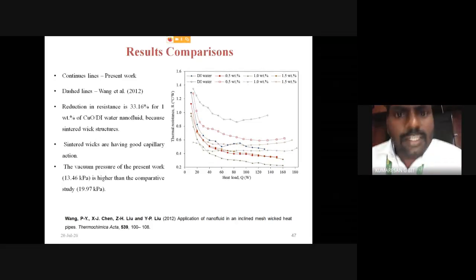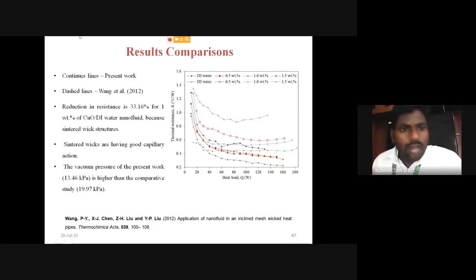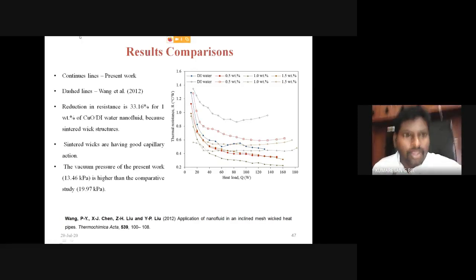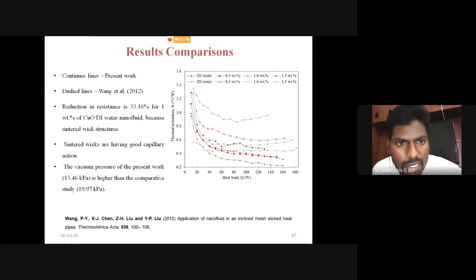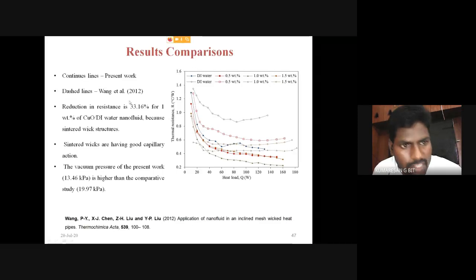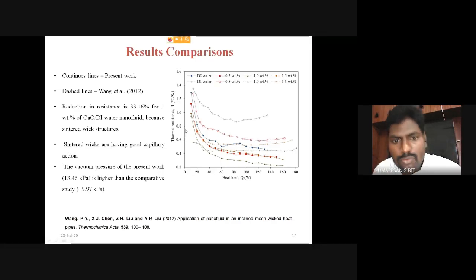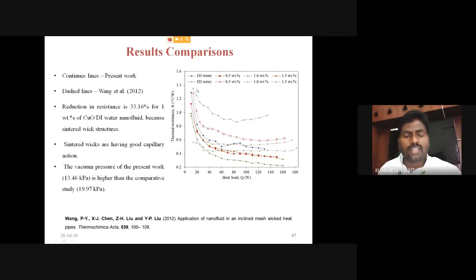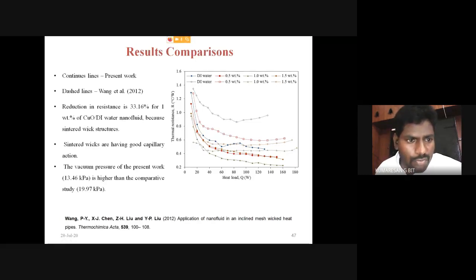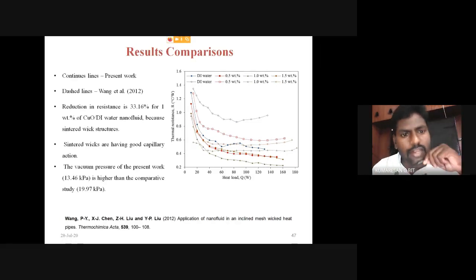Okay. Then results comparison with the existing work to validate the current results. The present work is indicated in a continuous line, and the Wang et al. study is indicated in a dashed line. You see the trend formation of the thermal resistance of the two studies. The thermal resistance gradually reduces with increasing heat input. Then a reduction in resistance of about 33.16% is attained for 1 weight percentage of the copper oxide DI water nanofluid,